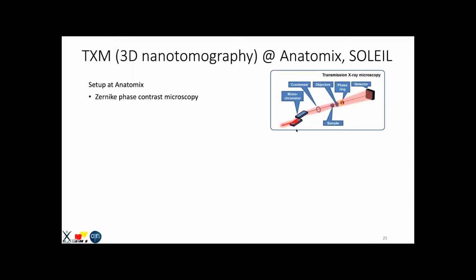So the way it works is you have a monochromatic X-ray beam that comes and is focused on the sample. It interacts with different parts of the sample. So there is the homogeneous matrix part of this 316 stainless steel and the precipitates that it interacts with in a different way. That results in a phase shift of part of the beam. And there is also the part of the beam that is unaffected. So there are three parts: one that is interacting with precipitates, one with the homogeneous matrix, and one with nothing.